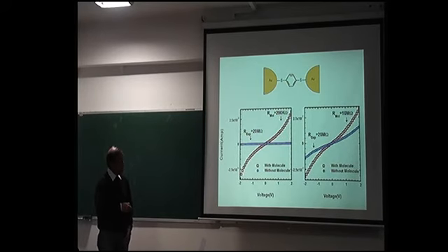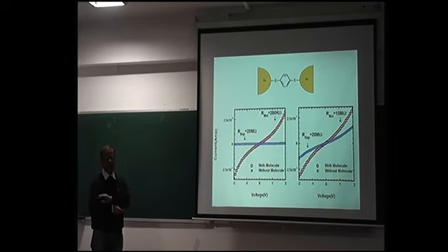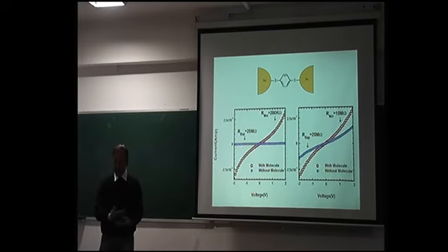So on a chip you should make at least 50 devices, or I would say as many devices as possible, and then take statistics and think of a kind of Millikan oil drop experiment. You will see there is a distribution of the resistance you calculate from the linear region. For example, here I show that this is 200 kilo ohm and this is 10 mega ohm. So there is a wide variation of the conductance of this gap. One can conclude that when it is a very high resistance, there must be 1 or 2 molecules, and when it is low, then it must be 10 molecules, because it's a parallel channel.